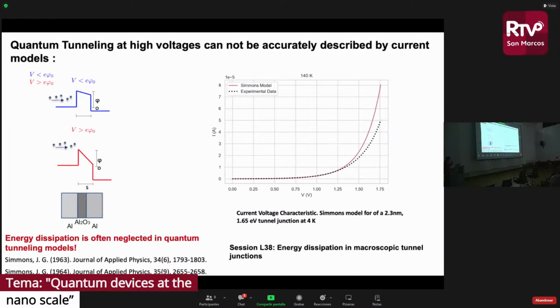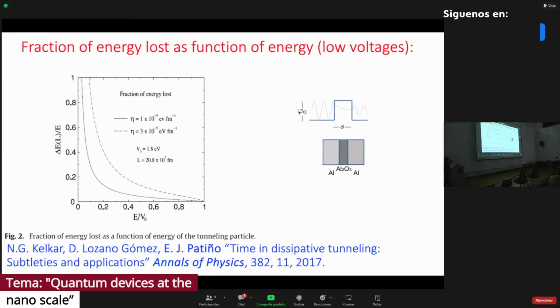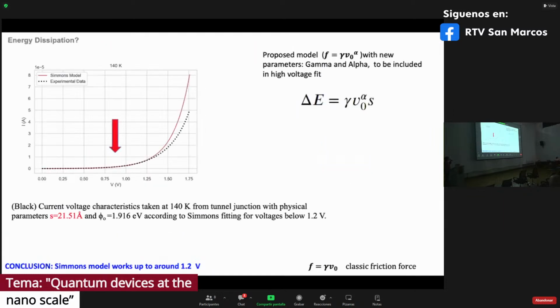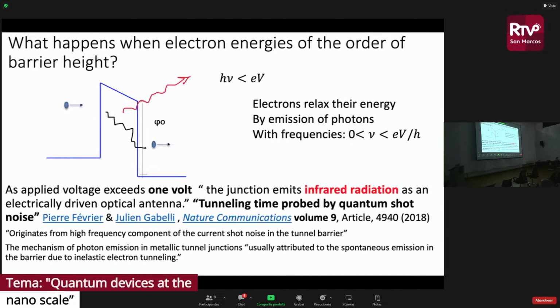We were devising a model to study dissipation, which is not included in the Simmons classical model for tunneling. We devised this model and published a paper on that. The important part to explain here is that when you look at the data and try to fit it with Simmons' model, it breaks down at high voltages. It works very well at low voltages, but at high voltages it breaks down, and that's related to how energy is dissipated in tunnel junctions. The model essentially includes the velocity of the particles and a gamma parameter of dissipation of the junction. Also, it's been investigated by Gabelli that when the voltage exceeds 1 volt, the tunnel junction emits infrared radiation. So it's not only heat, but also radiation at certain voltages. That's important to take into consideration.